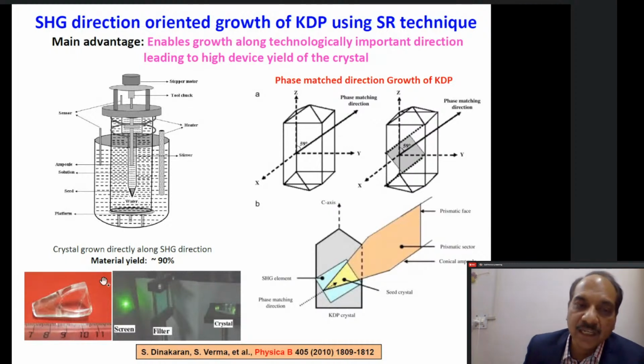The crystal was grown directly along the phase matching direction. The useful volume of the grown crystal was about 90%. So that was a great achievement. We were able to get this work published very easily, and reviewers also gave, I would say, encouraging comments on this new technology which was developed.